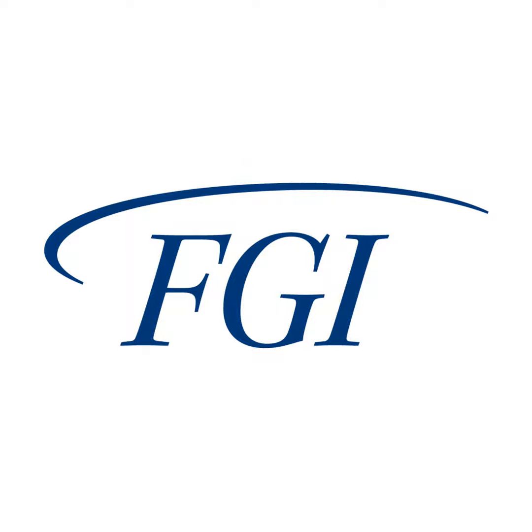Well, let's talk a little bit about how we get those OIT numbers. It's done with a device called a differential scanning calorimeter, or DSC. And the details differ slightly depending on whether we're looking at standard or HPOIT, but in both cases we're melting the plastic in a nitrogen environment at a changing temperature that comes up to an isothermal temperature. And in the case of the standard OIT, we then introduce oxygen at a pressure of 35 kPa, and the test is conducted at 200 degrees Celsius. In the HPOIT test, it's 3,500 kPa pressure and 150 degrees.